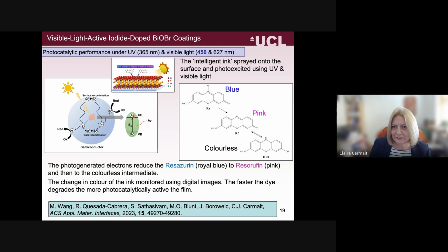And so you're forming electrons and holes. These then take place in the oxidation and reduction reactions. But what can often happen is that the electrons and holes can recombine either within the bulk or at the surface, and then that would limit or completely stop your photocatalysis. So often what people are trying to do is find ways to prevent that recombination, and one way you can do that is by tuning the band gap, and that can be from doping or forming heterojunctions.